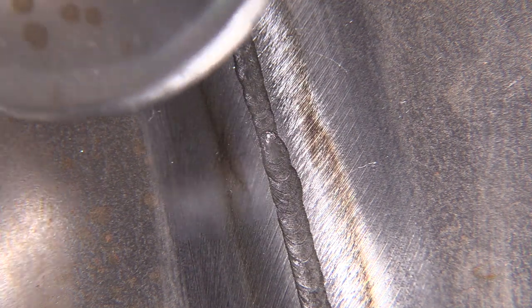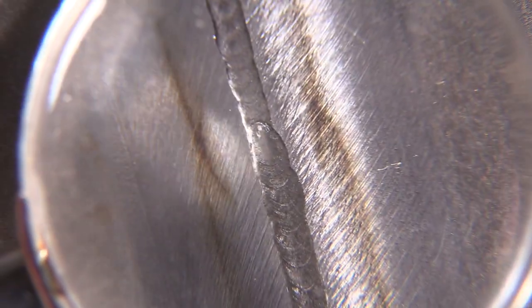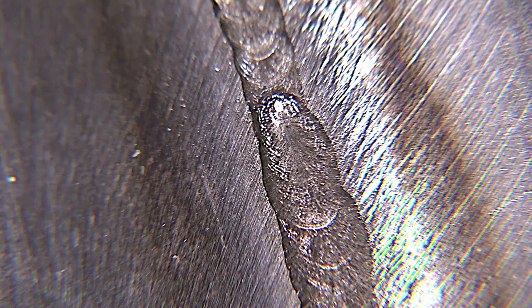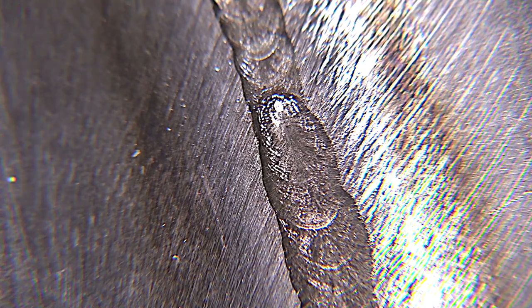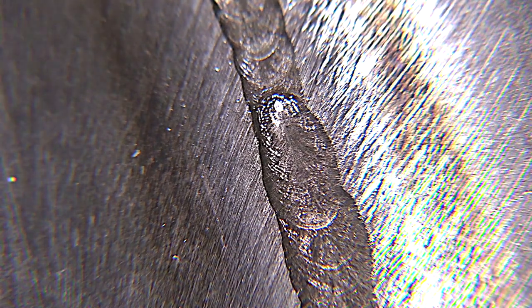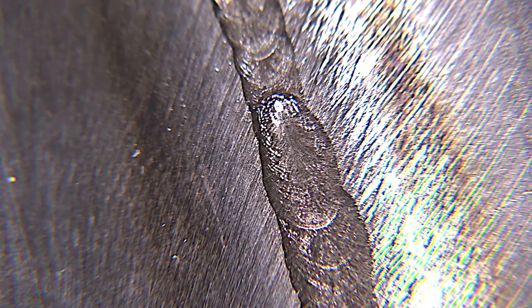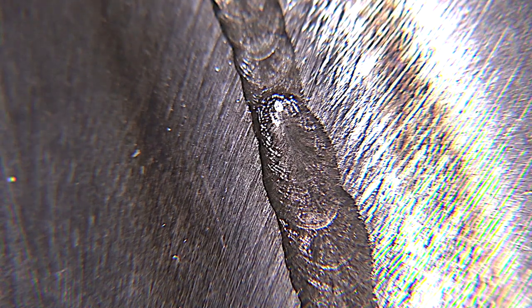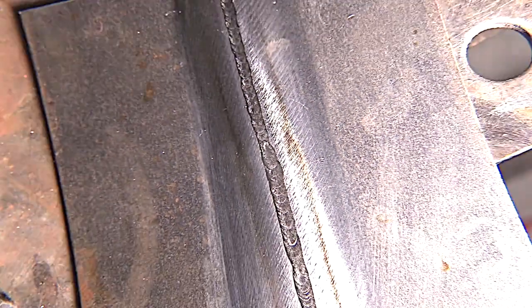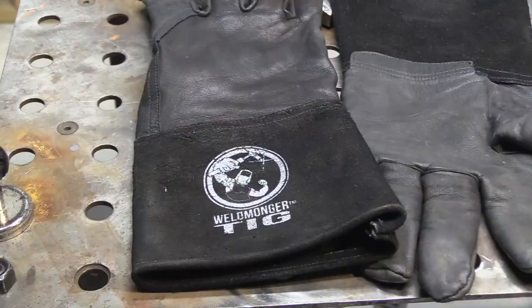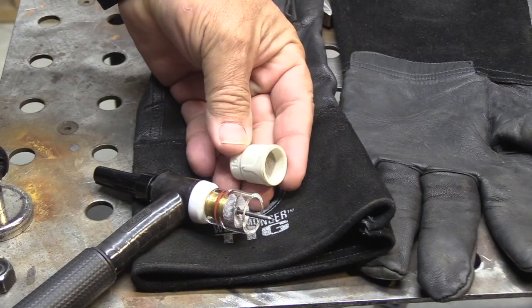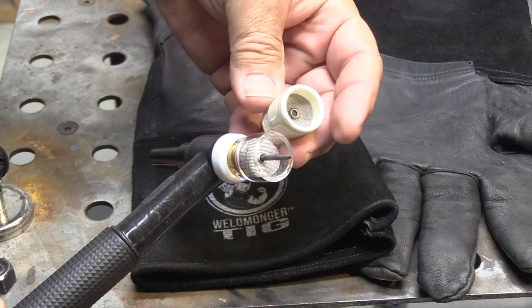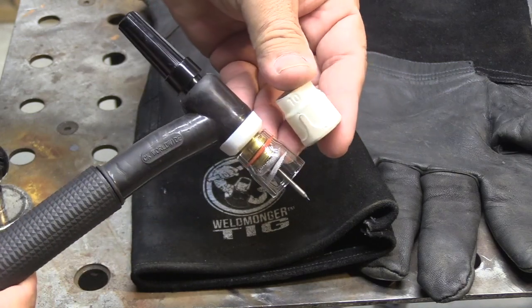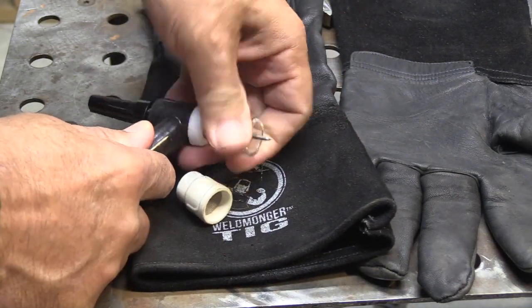And now let's take an even closer look with some magnification, and let's zoom in a little bit. That's where you're likely to have a crack right there. And it happens a lot on chromoly, on 17-7 stainless, on Inconel. But if you keep traveling as you taper off while adding less and less filler, you can avoid that crater crack. I'm going to swap over to the ceramic version of this cup right now and just show you how easy that is to do.